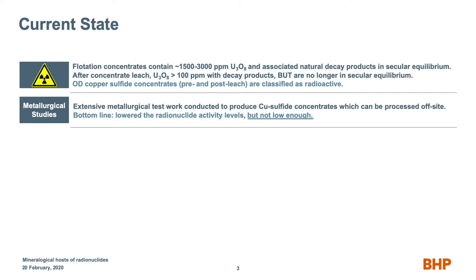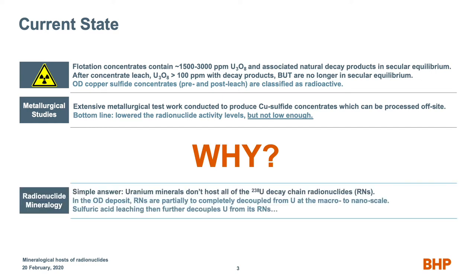However, we have done an extensive amount of metallurgical test work over the decades to produce copper sulfide concentrates, which could be processed off-site. No matter what we've done, we can lower those levels of radionuclides, but we can't get them low enough to easily treat them elsewhere. So we're not talking about marketability, but we just can't get them low enough so that they're considered non-radioactive. So you say, why? Why haven't we been able to achieve this?